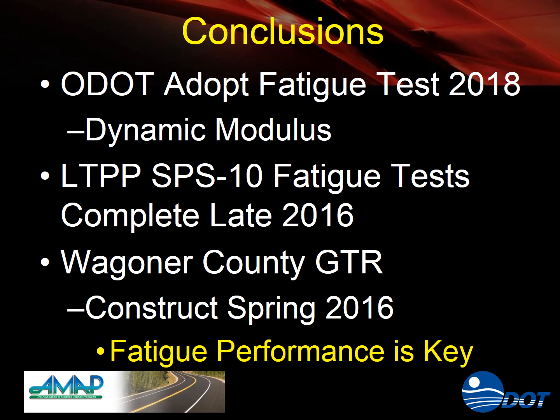We're also a sponsor at the NCAT Test Track for the cracking group experiment, which is also cooperating with MnROAD on some cracking experiments in cold weather climates. They also have some sections at NCAT where they're doing this fatigue work. So fatigue is the toughest nut to crack. I don't think you're going to see any specific test adopted nationally. It's hard enough with a rutting test. We have the flow number and Hamburg and APA and various rut tests. You're going to see the same thing with fatigue. Different DOTs and agencies are going to select their own fatigue performance test, but anything's better than what we have now. And when we add fatigue, I think we're going to exceed what the old Marshall and beam designs gave us. We're going to have a broad spectrum design, and we can actually increase the life of our pavements.